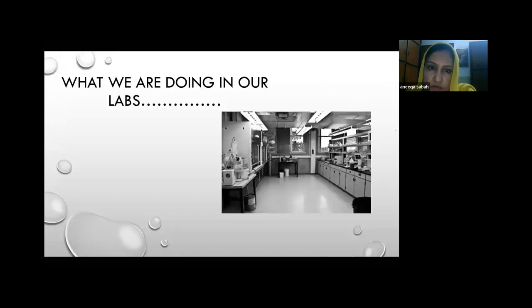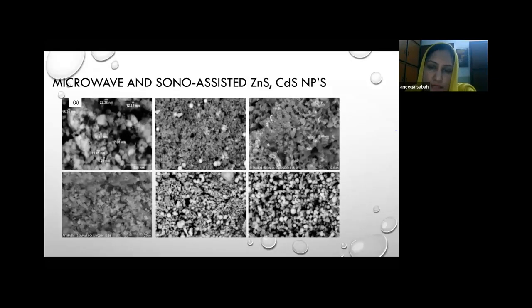So what we are doing in our labs nowadays, we have simply synthesized zinc sulfide and cadmium sulfide nanoparticles by traditional microwave radiation and sonochemical radiation under an ultrasonic bath, and even our sunlight. So we got different shapes and structures, spherical and spike-like, needle-like nanostructures, and these nanostructures are helpful, for example, in different applications with high surface area for sensing. In the last picture from the right, you can see the effect of sunlight, which is much better and more homogenized in comparison to all others, because the microwave radiations are fast enough in comparison to ultrasonic.